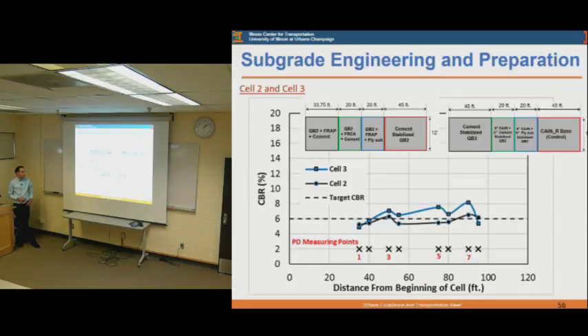And these are the final results for the subgrade engineering. The target subgrade was a CBR of 6. I'm not showing the individual trials here, but only the final trials for cell 3 and cell 2, and how they come closely to a CBR 6 subgrade for all the different measuring points before we constructed the different test sections on top of them.